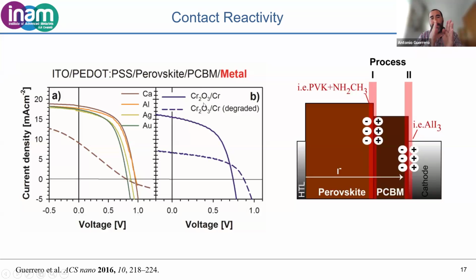So basically, these chromium layers were stopping the diffusion of ions, at least partially. So the degradation, or the type of chemical reactions that could be obtained, were stopped. And this is a clear case for reactive metals like calcium, aluminum, but also for silver. This is why most of the time we use gold, which is thought to be non-reactive, but in reality, it is also a little bit reactive, okay? So even gold, which is a noble metal, reacts with the ions coming from the perovskite. And the ions that typically migrate are iodides in the form of vacancies. And these iodides can give rise to electrochemical reactions with these contacts, giving, for example, aluminum oxides or silver iodide, and all this has been detected and reported in the literature.